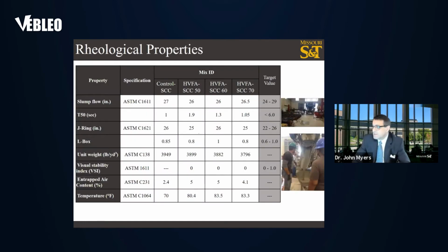A local ready mix concrete producer was used to help us produce the concrete. While making the mixtures, the dry materials, including the cement, fly ash, sand, and crushed stone, and 3/4 of the mix design water were added and mixed first at the ready mix plant and then brought to our structural engineering high bay lab. The following tests were evaluated to assess the fresh concrete properties of the concrete and compared to the target values to meet the rheological properties of the mix design.